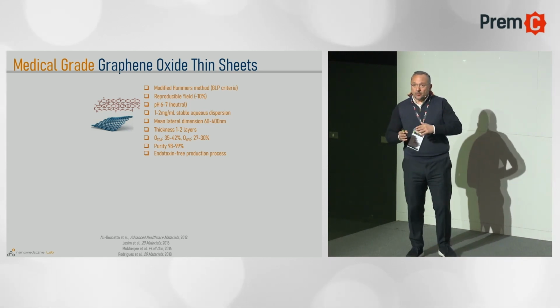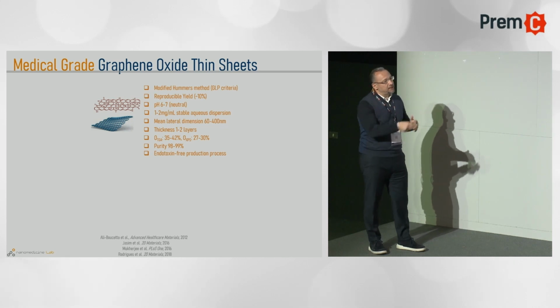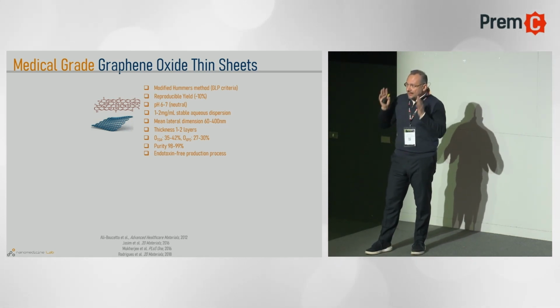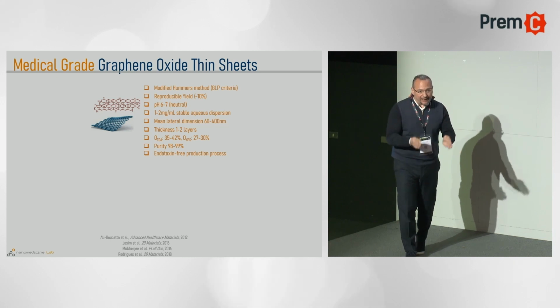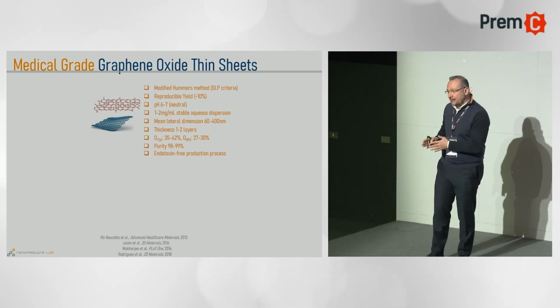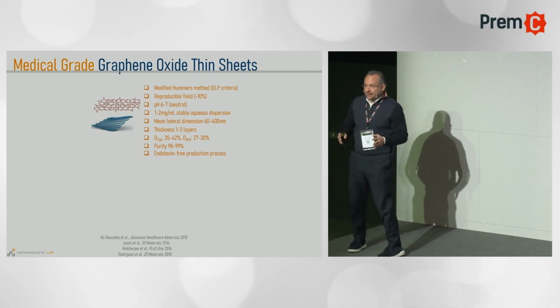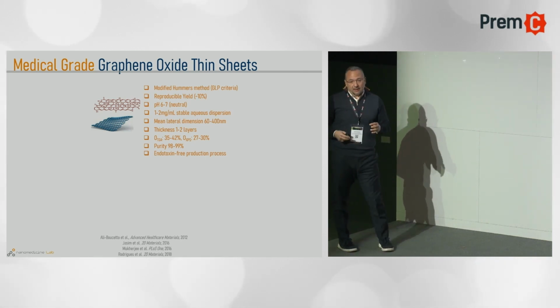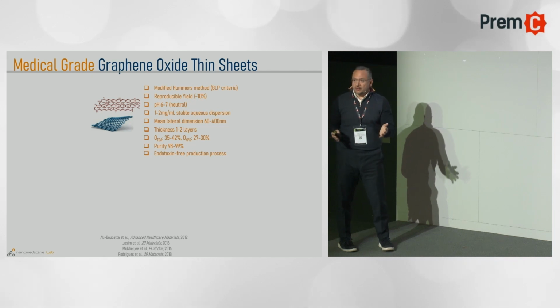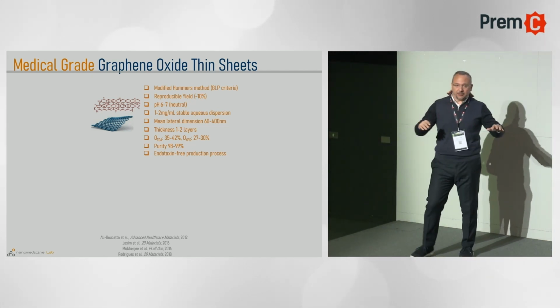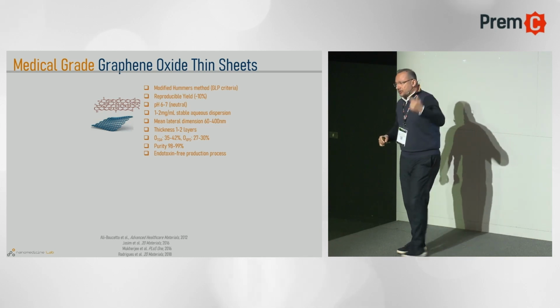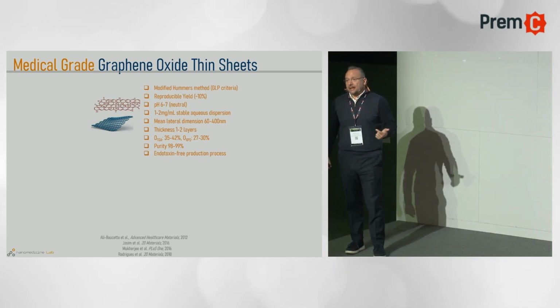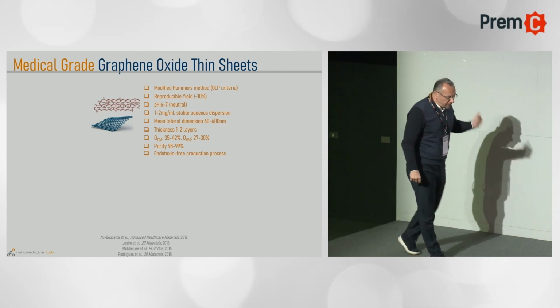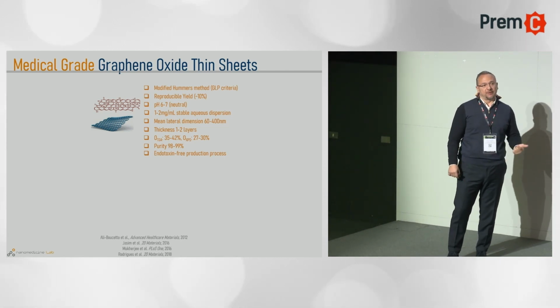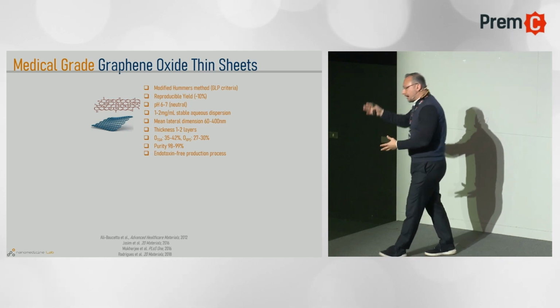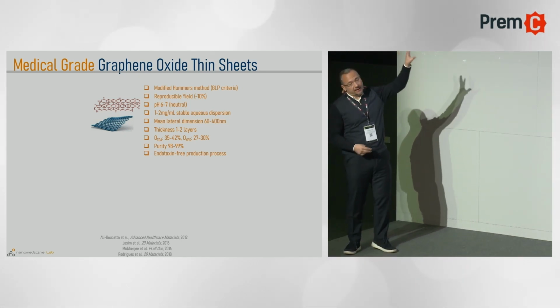So the first thing we did is we invested a lot of time, and you see all of these papers that are kind of reflecting this effort, in order to identify and establish a clinically, what I call a clinical grade, a medical grade graphene oxide material. What do I mean by that? Not only to comply with this bracket of properties that you see here, so extremely thin material, very well surface characterized, but also to have this kind of batch-to-batch reliability and reproducibility. And we are making sure that every time we make a new batch of materials in the laboratory, or if we upscale, we always maintain this set of parameters.